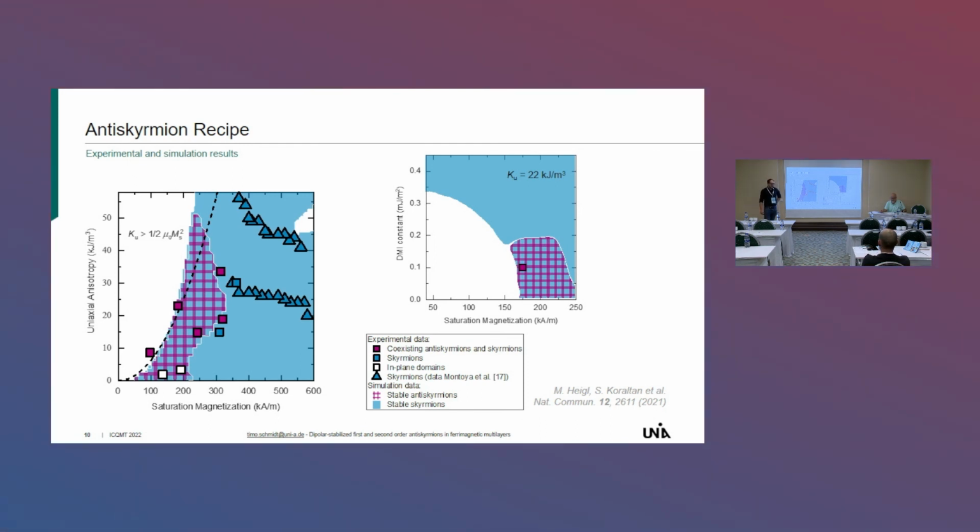It definitely reduces the saturation magnetization, because we had films without and with some iridium layers, and the saturation magnetization goes down. What the reason for this is, I'm not sure, but basically we don't have DMI as we expected. I hope that somehow answers it.